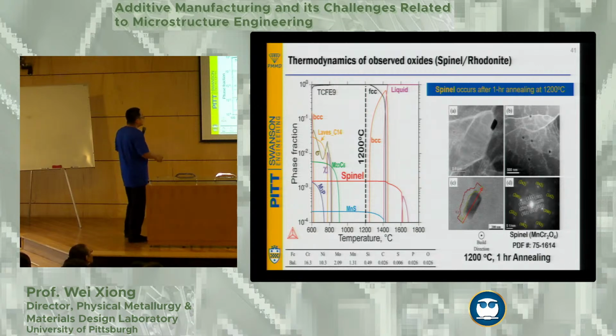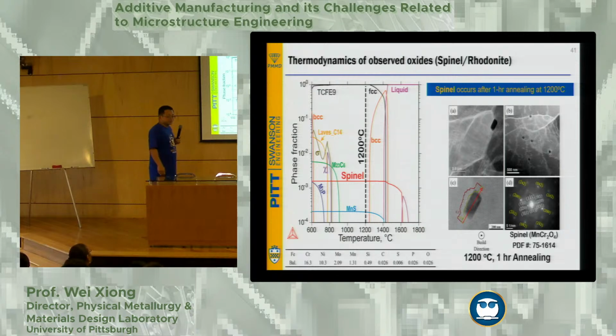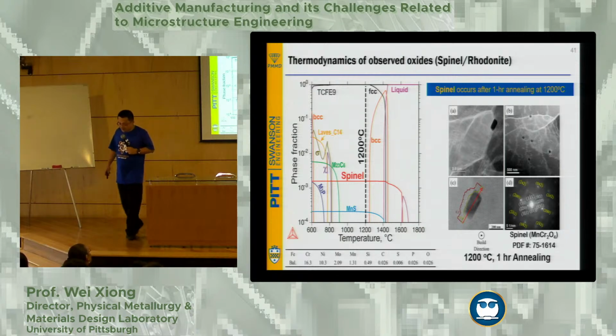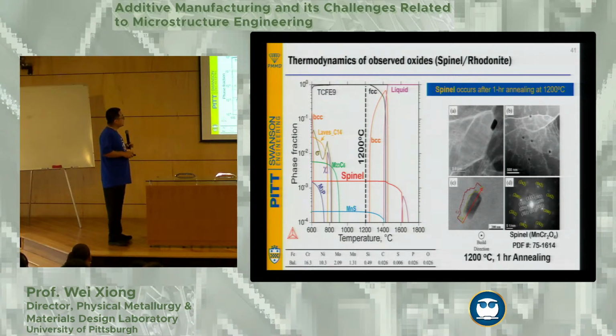So we quantify - we did some EELS in the STEM, and we identify these particles are actually spinel, with manganese chrome. And then we calculate.